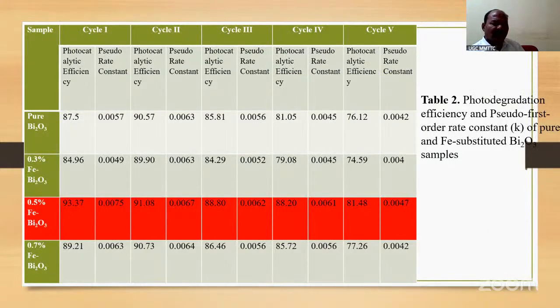Now this is the case. Here the photodegradation efficiency and pseudo first order rate constant of the iron substituted bismuth oxide samples. This is the pseudo first order rate, the photocatalytic efficiency and pseudo rate constant, in the photocatalytic efficiency cycle 1, cycle 2, cycle 3, cycle 4 and cycle 5. Here the same thing for the first, second, third, fourth and fifth cycles of the materials.